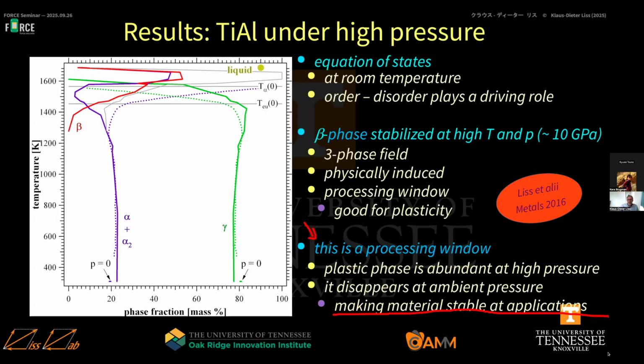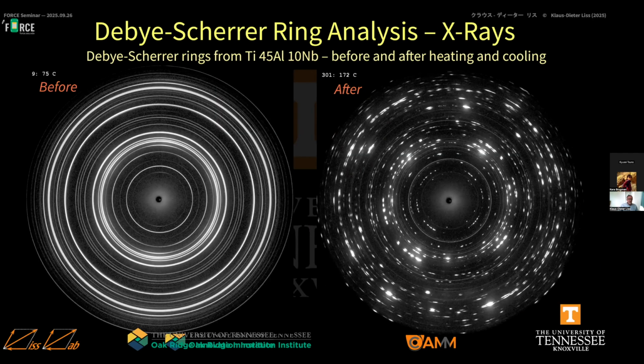Time is running. Let's go on. So let's look also to the Debye ring analysis, in this case for X-rays. So here are Debye rings from titanium 45 aluminum 10 niobium before and after heating and cooling. So we take the material, we have this diffractogram, these Debye rings, heat it up, and then we cool down and we get that. And you see already the stunning qualitative difference.